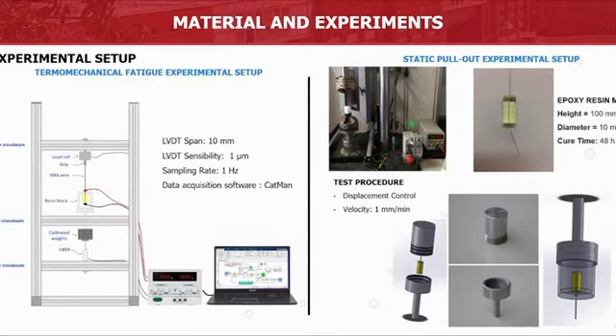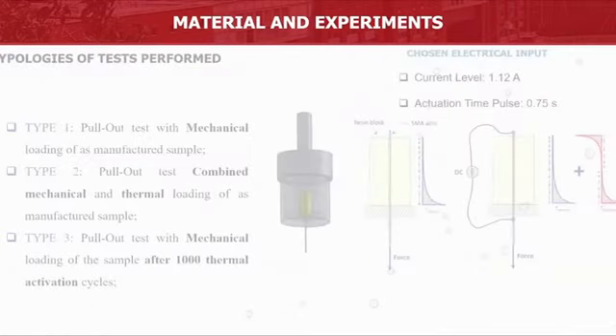For the static pull-out purpose, we use a tensile test machine, obviously, and the test procedure is a displacement controlled test with a movement velocity of about 1 millimeter per minute. The sample is an epoxy resin cylinder with a height of 100 millimeter and an external diameter of 10 millimeter with an SMA wire of 0.3 millimeter embedded in it.